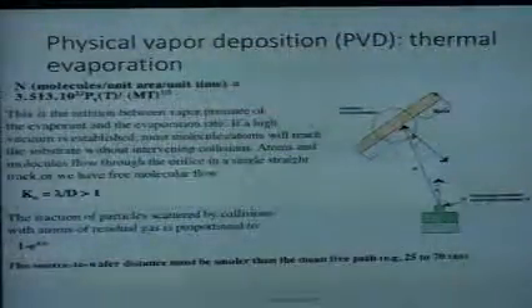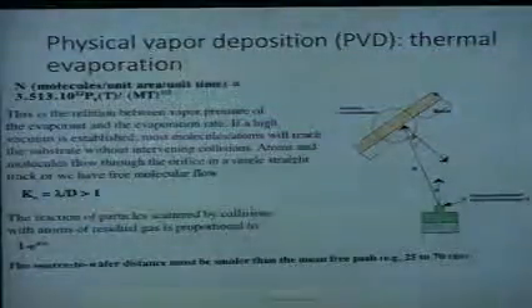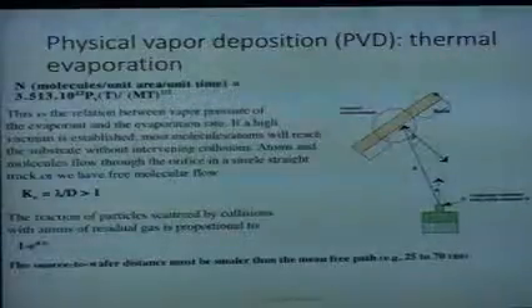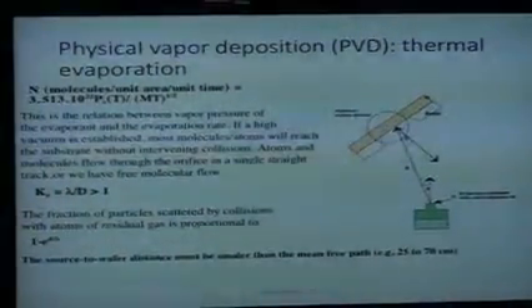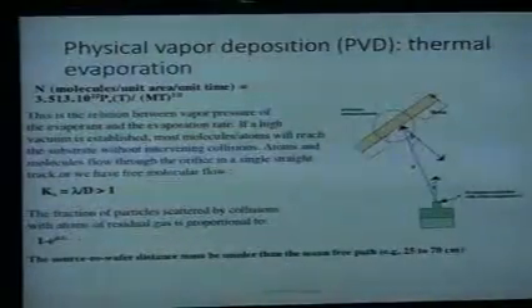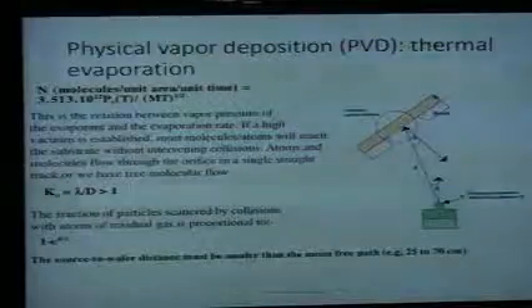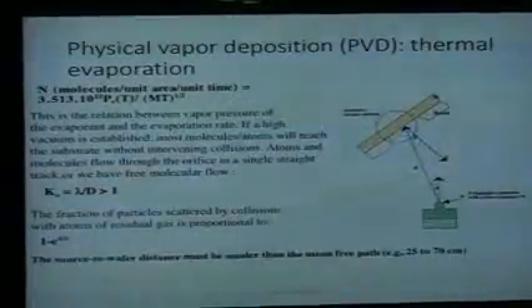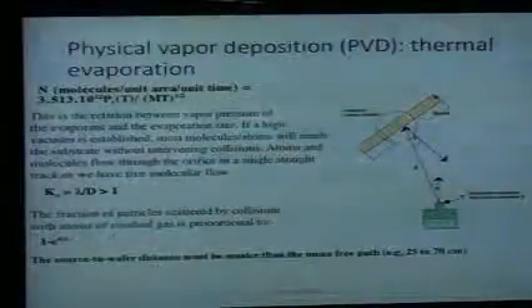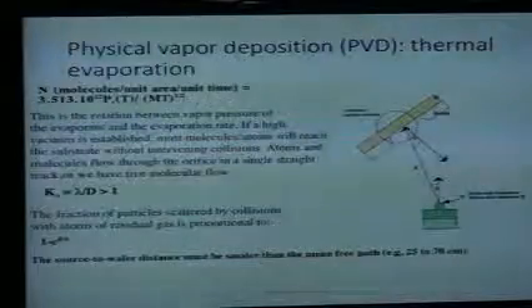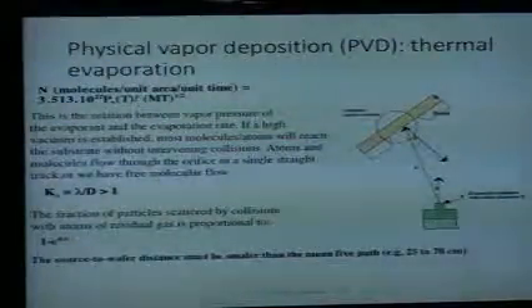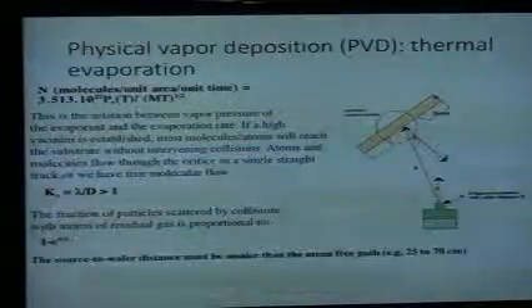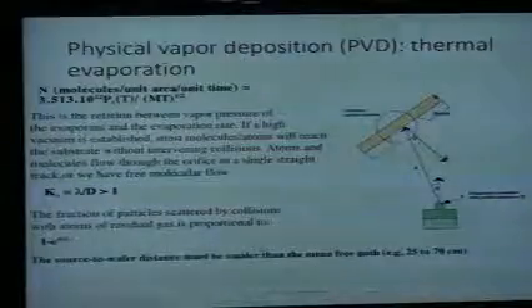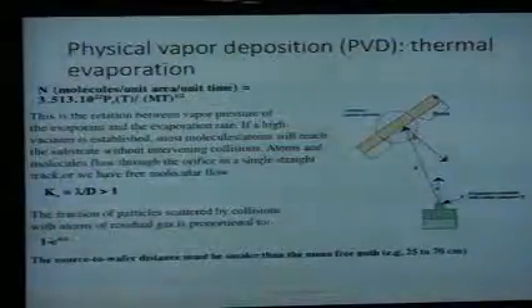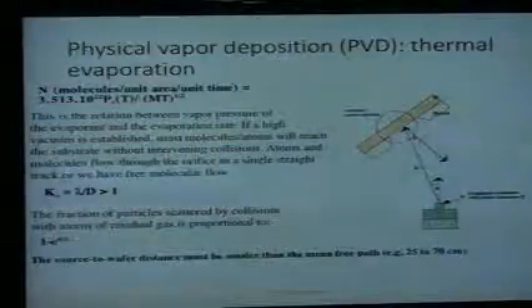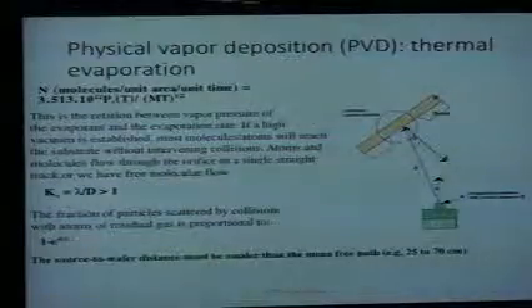This is another way of looking at it. In general, you'll have your deposition surface, you have your evaporator. You'll do some things with your evaporator. In physical vapor deposition processes, you try to make it line of sight. Again, if your mean free path is longer than the distance that separates your target and your deposition surface, then you can get line of sight. You can get straight-walled types of deposition processes. So one of the things that you want to be able to do is, this is a Knudsen number, the Kn term here. That's the mean free path divided by d, where d is the orifice diameter of your evaporator container.